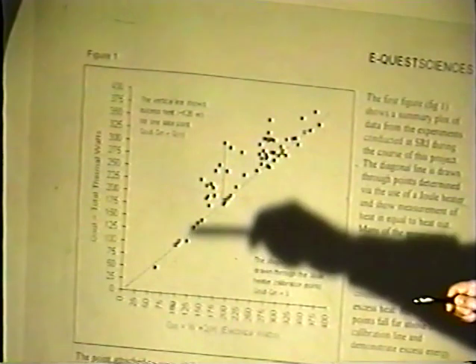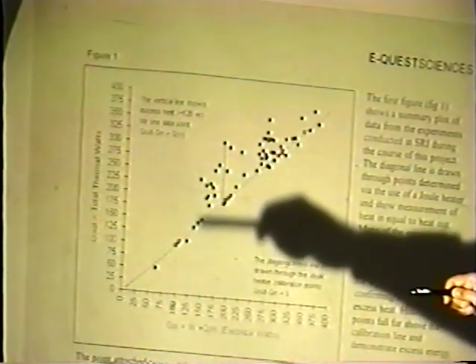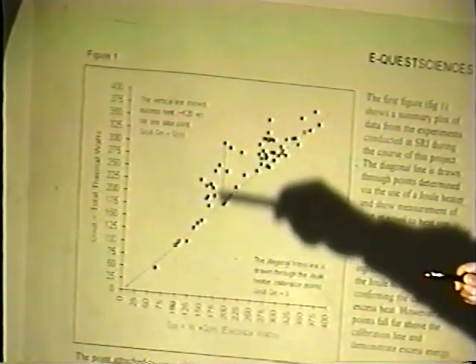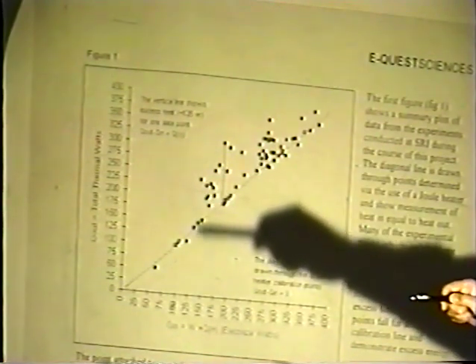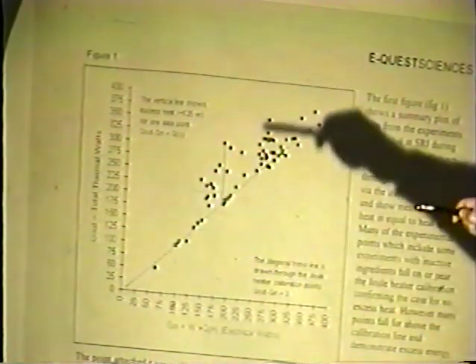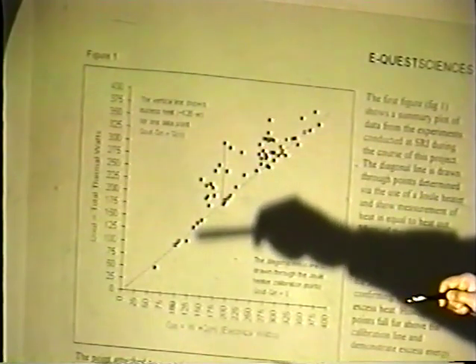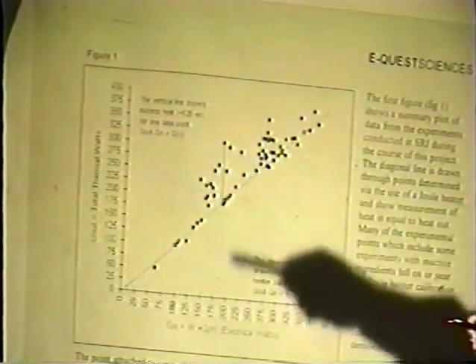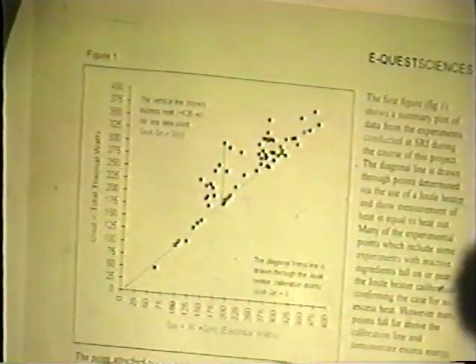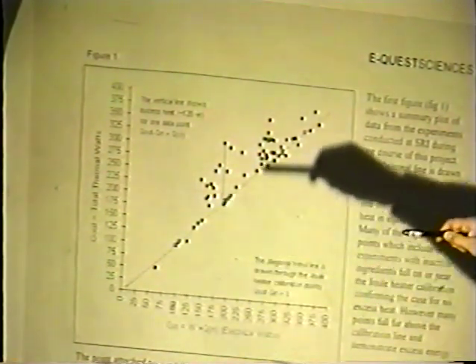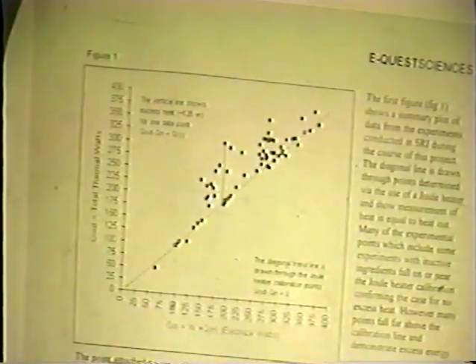Whereas on these experiments here, these were all mainly palladium heavy water experiments. There were very few titanium. This is a titanium experiment. There were a number of these experiments that make the best controls because they were palladium heavy water experiments that we expected to work, and they didn't, and they fell on the calibration line. So we have a good scatter of success and failure in the same system.